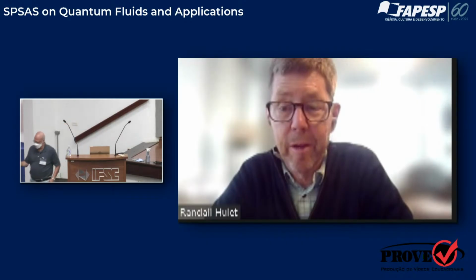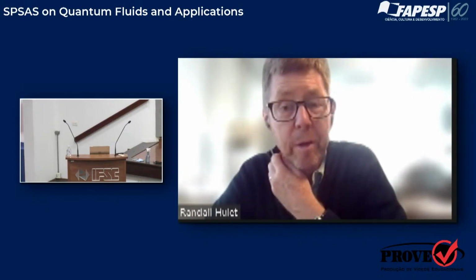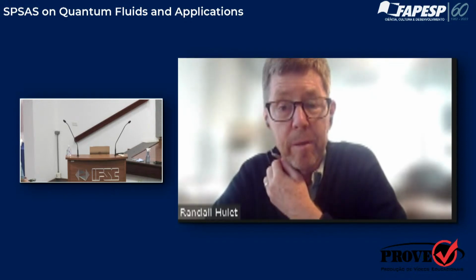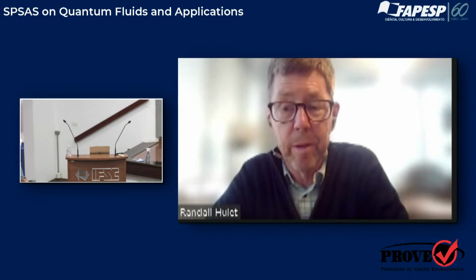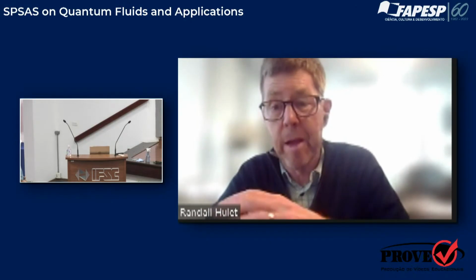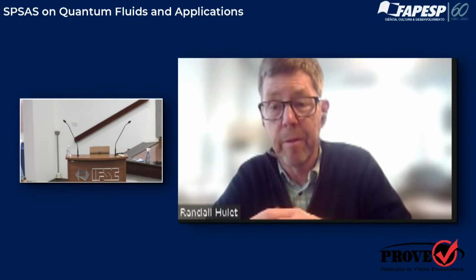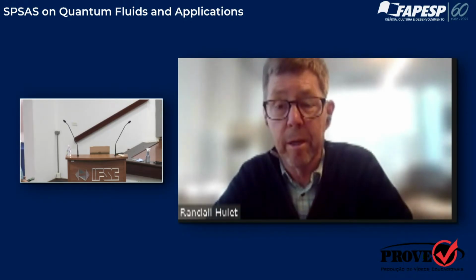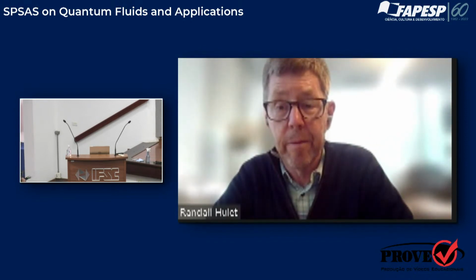Yeah, okay. Great question. So the magnetism seems to underlie superconductivity in these unconventional superconductors. It seems to be the case that every high TC material we know, or certainly most, have this phase somewhere near the superconducting region of the phase diagram. So there is something about antiferromagnetic order which is important to the way that these materials become superconductors. And so the motivation is to understand the Hubbard model and all of its regions in the phase diagram of doping versus temperature, but also to understand if there is some connection between superconductivity and magnetism, how we can exploit that connection to make even higher temperature superconductors.